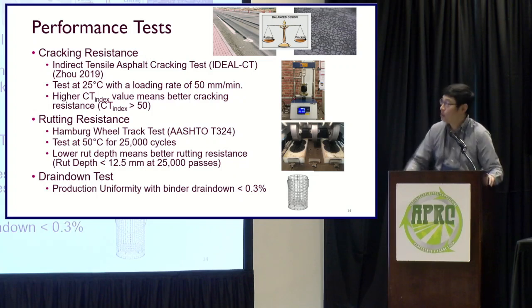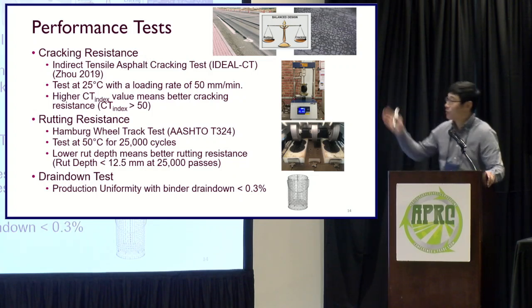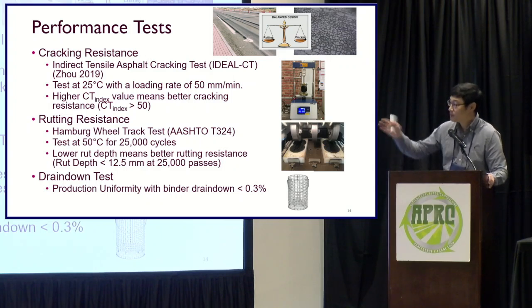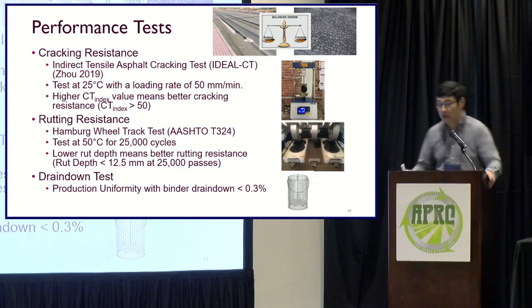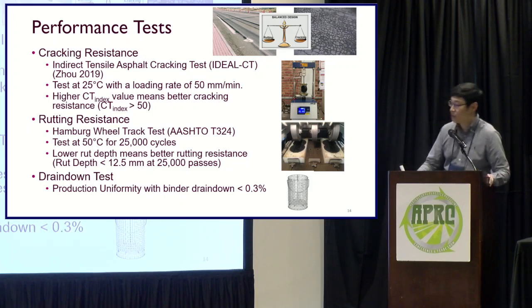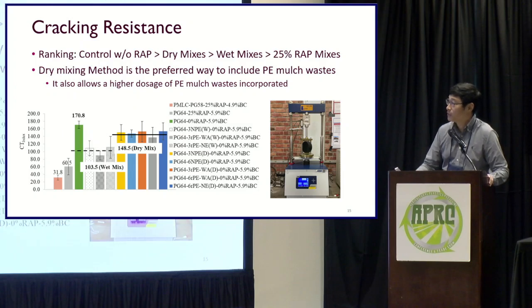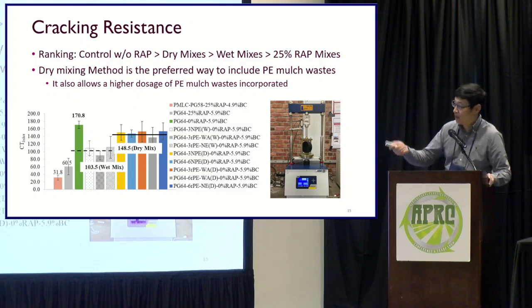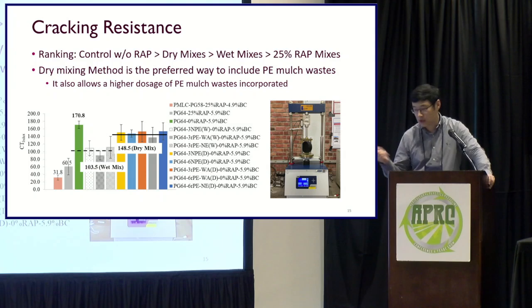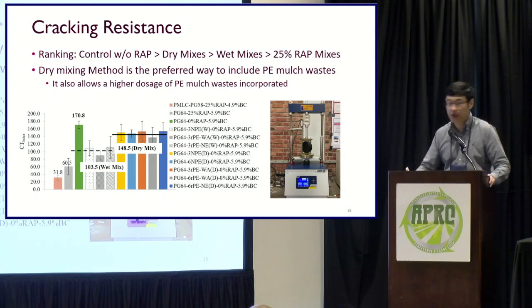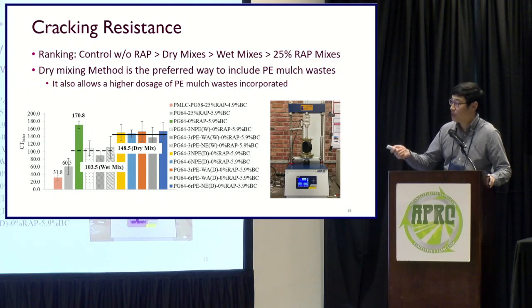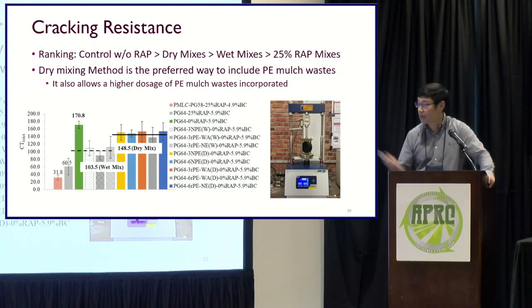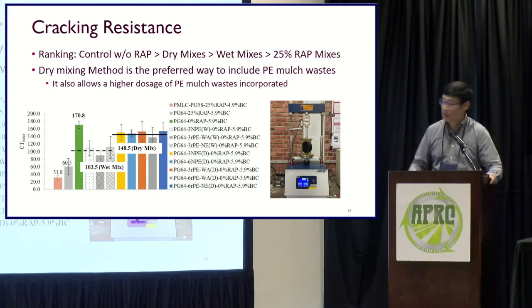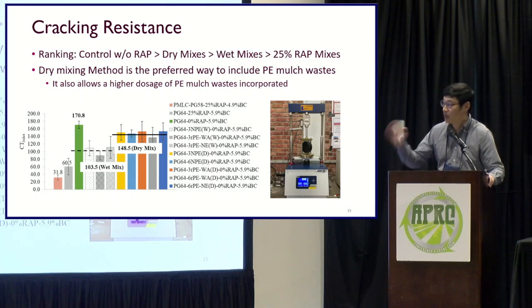And then, as I mentioned, 2 big issues for the asphalt pavement, rutting and cracking. So we do the cracking resistance test using the IDEAL CT, rutting resistance following the standard, and run the Hamburg test for the rutting resistance. And also, we do the drain down test to determine the production uniformity when we add the plastic into the asphalt. So cracking resistance, if you look at the control mix with a recycled material with a RAP, it has an IDEAL CT around 32, which is less than 50, so that's a really brittle material used currently. Well, when we have the control mix without the RAP, we have the 170 CT index, so that's a really good number. So yeah, the 50 is a limit, so we have much higher than the 50.